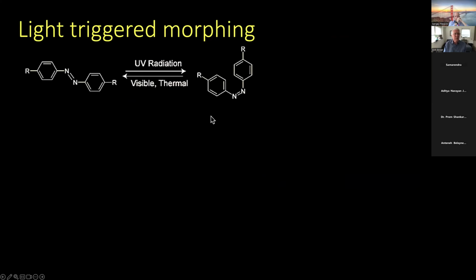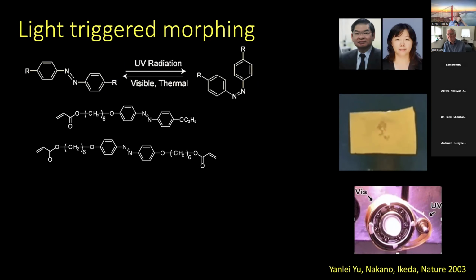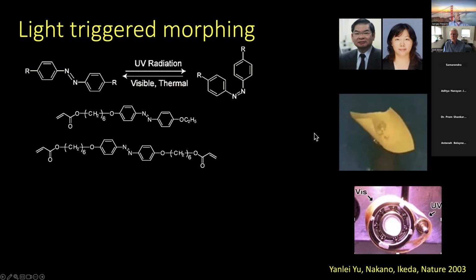common material that is used for that is an azobenzene molecule, which can go from a trans state to a bent cis state in a reversible way, just by exposing it in the absorption band of either the trans state or the cis state. And for that I should mention actually the work of Tomiki Ikeda and Yanlei Yu at the time in around 2000, where they created liquid crystal films that they could address by polarized light, and then, making use of this polarization sensitivity, you can actually change the direction of deformation by changing the polarization of the light.